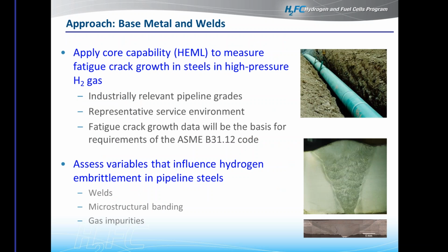So the approach that we're taking is here at Sandia, we have our core capabilities in our hydrogen effects on materials lab, and we're able to perform these tests in high-pressure hydrogen gas. And so we're choosing industrially relevant pipeline grades, and we're testing them in a service environment that we anticipate these hydrogen pipelines to be exposed to. So the fatigue crack growth data that we generate is the basis for what's going into the ASME B31.12 code, which is the code that, as I mentioned earlier, will be used by a pipeline designer to spec out what size thickness and what size diameter, all of these specs that will be necessary if they're wanting to put in a hydrogen pipeline.